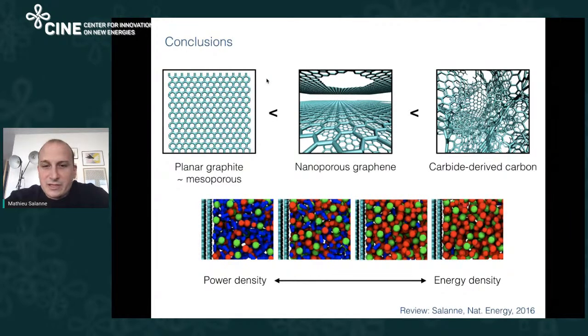Then on the side of the electrolyte, ionic liquids are much better for energy density because they have a high operating voltage. But for larger power densities, it's better to have acetonitrile or another organic liquid because it will increase the diffusivity of the ions and so it will lead to better power density.